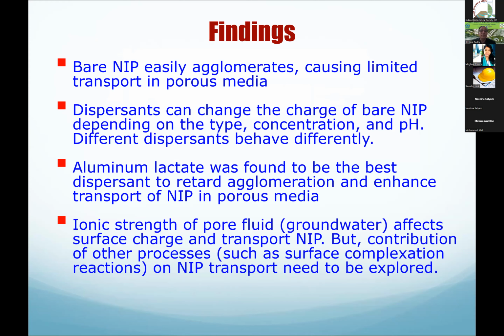So what we found based on these experiments is that bare nano iron easily agglomerates and it will not be able to transport in the porous media. And dispersants will change the charge of the bare nano iron, depending upon the type, concentration, and the pH. Different dispersants behave differently, as you saw. Out of all these, what we found is aluminum lactate. We are lucky to find at least one that is robust, prevents agglomeration, and allows the transport of nanoiron particles in the porous medium.